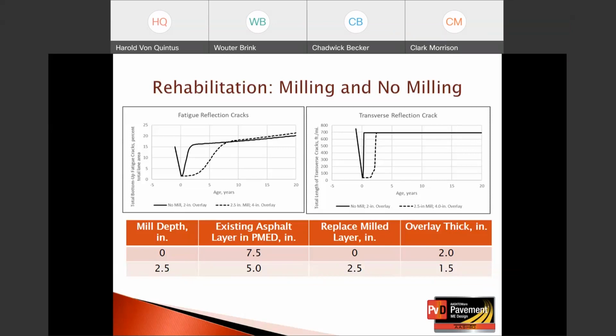And so the dashed black line shows the predicted fatigue cracks measured over 20 years. The graph on the right shows the same thing, but for transverse reflection cracks. So the 4-inch overlay in this case didn't provide a significant delay in those transverse cracks that existed in the existing pavement.